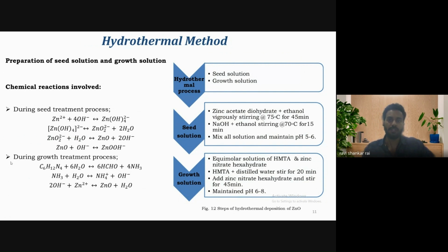In the seed solution, we prepared a combination of zinc acetate dihydrate with ethanol and sodium hydroxide with ethanol, and we mixed the entire system at 70 degrees Celsius for 15 to 60 minutes. We have maintained the pH between 5 and 6. Also, there is a growth solution, which is an equimolar solution of HMTA and zinc nitrate hexahydrate in distilled water, maintained at a pH of 6 to 8.